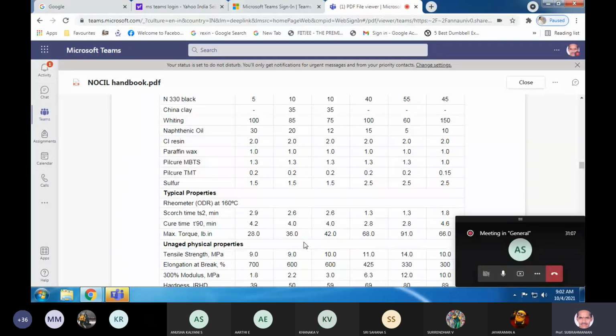Once the rubber allyl hydrogen is sufficiently activated, and I have created the right situation in the rubber to respond to the insertion of the sulfur, that time TMTD also promotes the thiazole. After all, this is the MBTS, TMTD and sulfur combination.